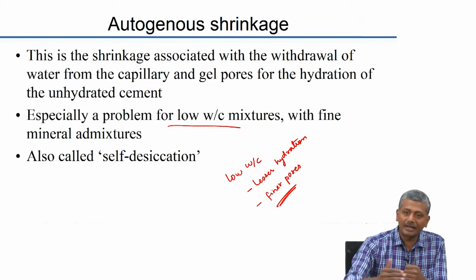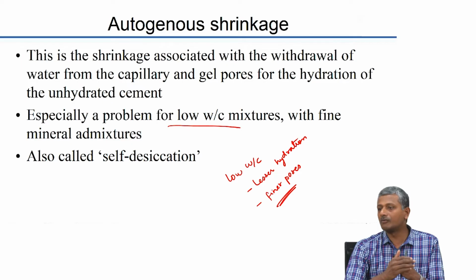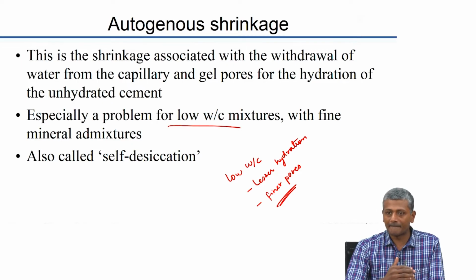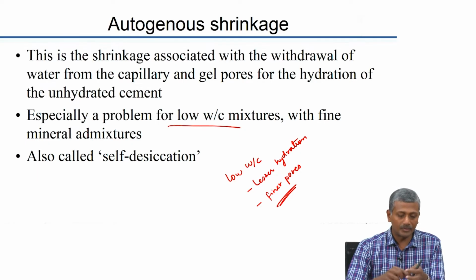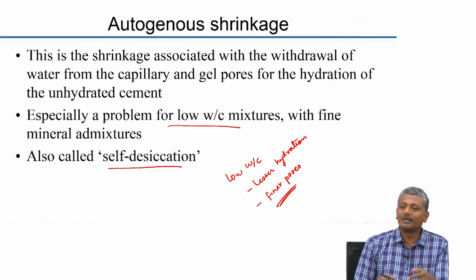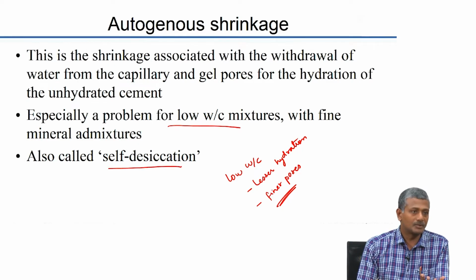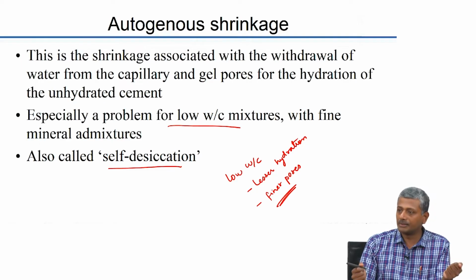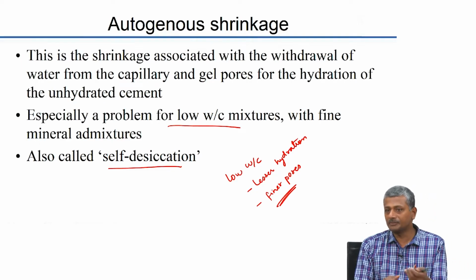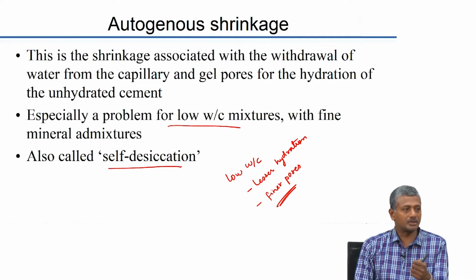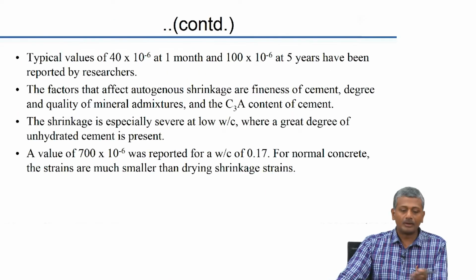When you do a greater extent of wet curing, the amount of autogenous shrinkage keeps reducing, okay, because water is available from the outside, it reduces the amount of capillary pressure that is felt by the system upon self desiccation. Again, it is called self desiccation because there is drying happening from within, you do not necessarily need to dry it outside. So, even in a sealed specimen you will actually get shrinkage, and that is because of autogenous shrinkage.